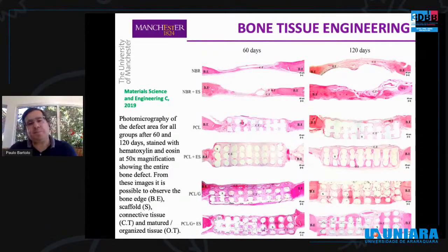In the case of PCL scaffolds with and without electrical stimulation, we observe the formation of a connective tissue around the filaments of the scaffold, and also islands of new bone embedded in this connective tissue. And by applying electrical stimulation, we observe a much more organized new bone being formed. In the case of electroactive scaffolds, with and without electrical stimulation, we observe much higher levels of new bone and also much more organized.